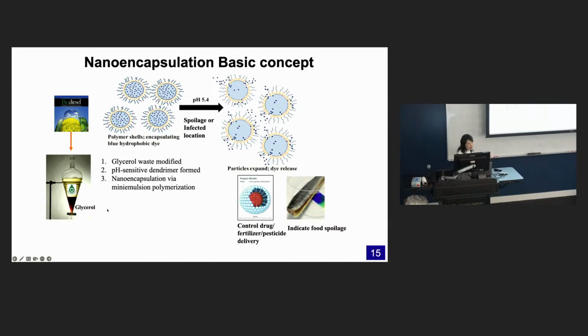And the second step is we encapsulate food-safe dye inside this using what we call mini emulsion polymerization. The mechanism is that they can achieve the nano-encapsulation. And also make sure that you have a one-to-one copy before your polymerization and after polymerization. And because we react with diamine, our surface is pH sensitive as well.